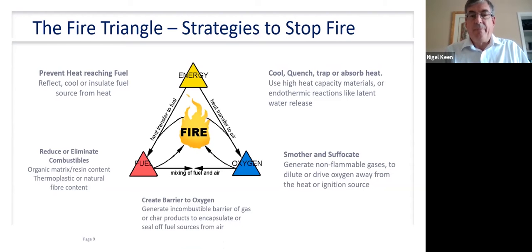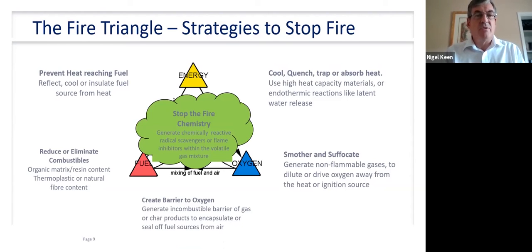And finally, we can stop the fire chemistry. We can suppress the flame by putting chemically reactive agents into the vapors and snuff out that exothermic reaction that requires the free radicals. So we can put things like bromine and chlorine gases, or free radicals, into the gas, and that will soak up the OH and oxygen free radicals that are part of the fire chemistry. So they can snuff out the fire quite easily.